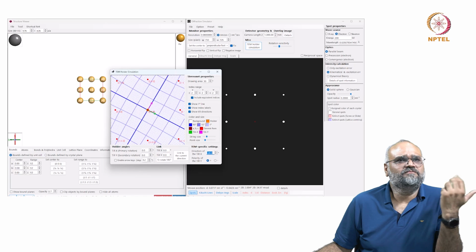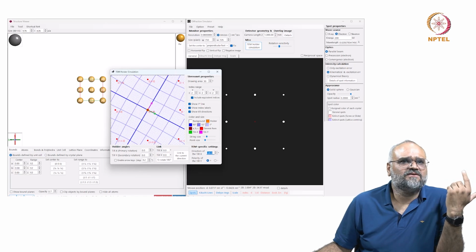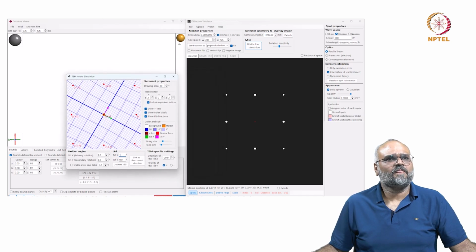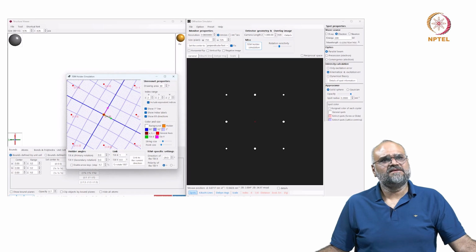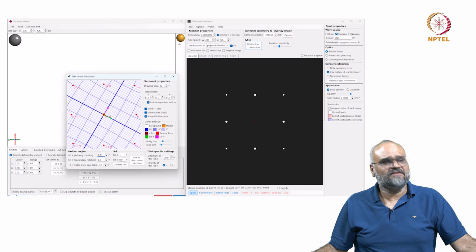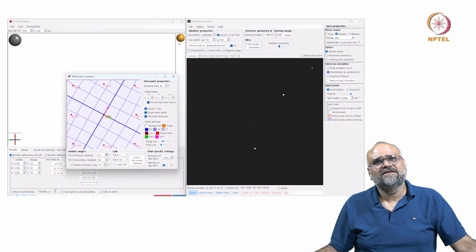So let us say primary tilt is the X tilt, and if I tilt through 1 degree in x-axis direction, I can show you how the diffraction pattern changes. By doing a 1 degree tilt, the symmetric pattern which I had like this changes, so let me do even a smaller tilt, because here is where you know that the Bragg angles are so small that even a 0.1 degree misorientation kind of offsets my diffraction pattern like this.